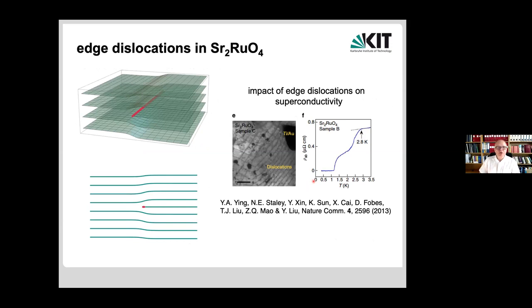So edge dislocation, which is what I mentioned earlier, and what we propose here, is something that has been seen in strontium ruthenate quite a bit, and the impact of it was actually investigated a number of years ago, even pointing out that if you have a high concentration of them, you would get local Tc values or onsets of superconductivity at a much higher temperature, somewhere near what can be reached in a much more honest and beautiful way using homogeneous uniaxial strain. So there are those dislocations in the system, and they do couple strongly to superconductivity.